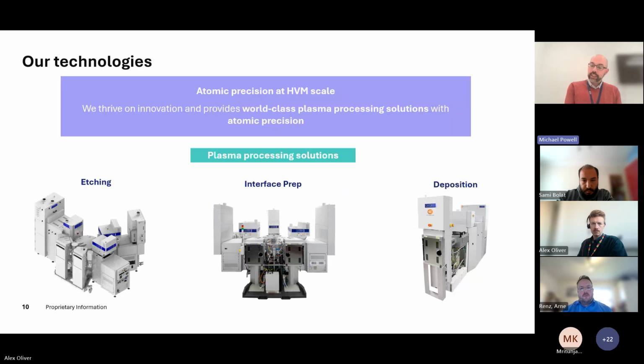And within this, where do we sit with our technologies? So our technologies are all based around either adding or removing materials and being able to do that at speed with control. So on the etch side, we are primarily based on ICP and reactive ion etching. On the deposition side, we have some ICP technology. We also use capacitively coupled plasmas as well. And then in between, it's how do you get the interface correct? So what can you do in order to ensure that the material is ready to be processed? Can you get back to a high quality interface before you do a dep or an etch? And how do you control things? So we all come back to control in the end. Next slide, please.